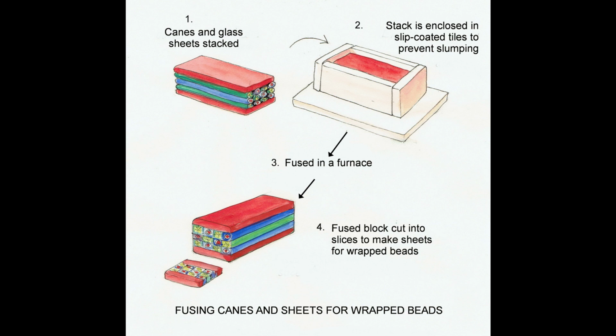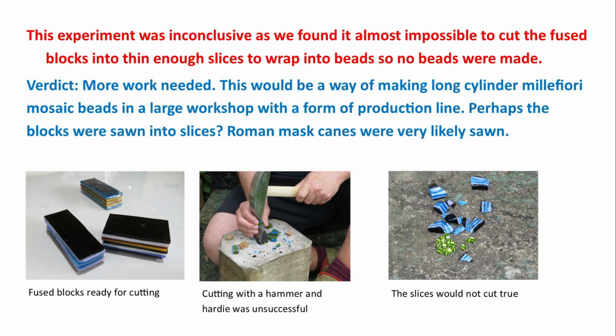In the second wrapping method, whole canes are stacked and fused in a furnace to make a block. Slices cut from the block are wrapped round the mandrel as in the first method. This experiment was inconclusive, as we found it almost impossible to cut fused blocks into thin enough slices to wrap into beads, so no beads were made. The verdict: more work needed. This would be a way of making long cylinder millefiori mosaic beads in a large workshop with a form of production line. Perhaps the blocks were sawn into slices? Roman mask canes were very likely sawn.